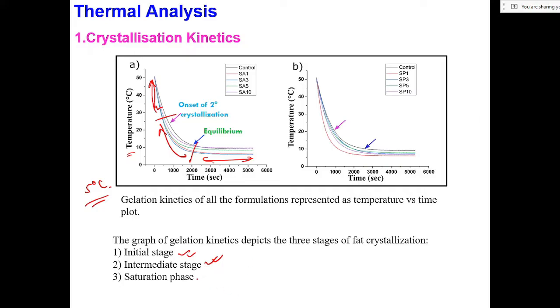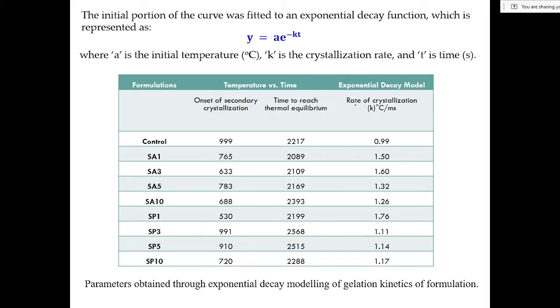Okay, so that is the saturation phase. So in all of these things, we saw that the addition of emulsifiers has altered the crystallization kinetics. Now from there we calculated the rate of crystallization. If you see, with respect to the control, when we added the emulsifiers, whether it is a low HLB value emulsifier or a high HLB value emulsifier, all of them have increased the rate of crystallization.